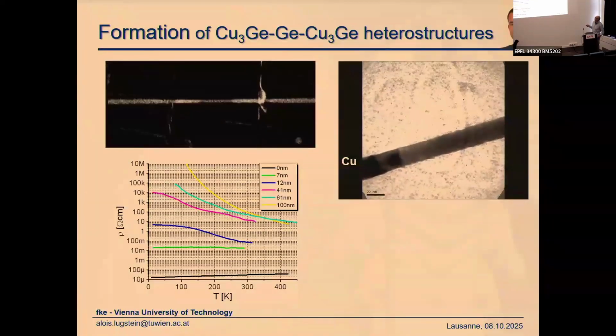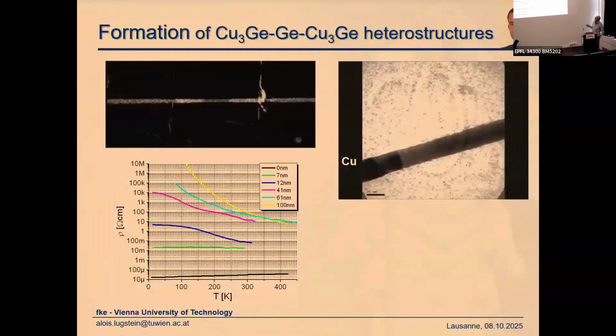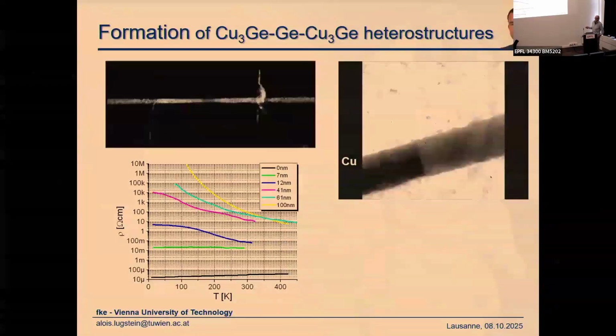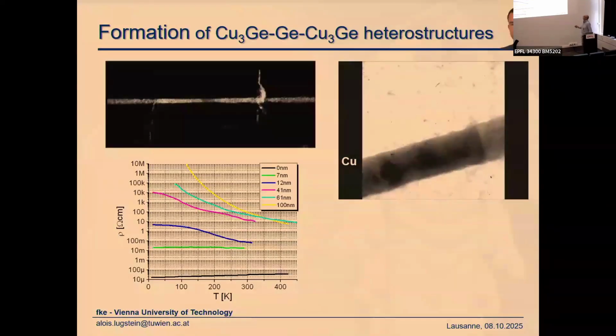And if you heat up the structure, you see that these bright extensions are formed, which arises as the copper is diffusing into the germanium nanowire, forming a copper-3 germanide, which appears bright in the SEM. And happily, the interface in between this quasi-metallic copper-3 germanide and the germanium is abrupt, more or less atomically abrupt. So by that, you can make nice contacts. This behaves like a metal.